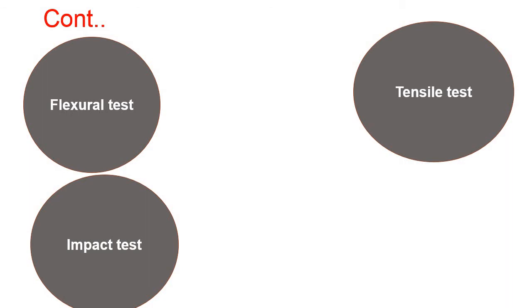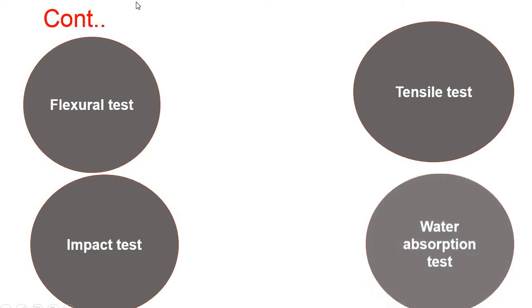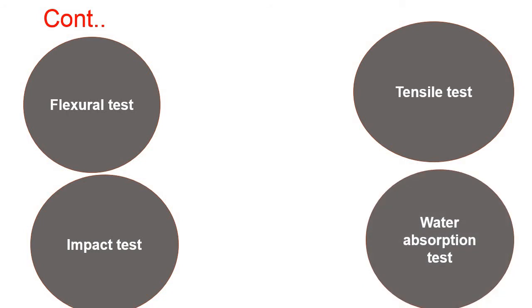And then we will go for the water absorption test. In the water absorption test we are using the ASTM standard ASTM D570. What we are going to do is the specimen of the fiber composite was immersed in water for more than 72 hours, and the change in weight of the composite material is recorded every 4 hours, in a periodic manner.